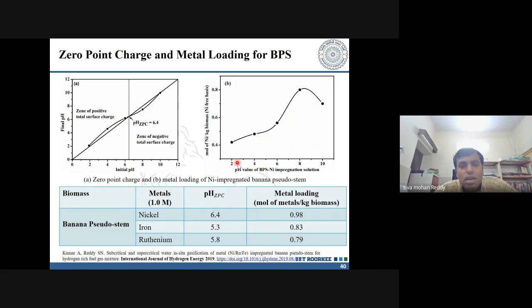You see this is pH, and this is the mole of nickel per kg of biomass. Now, even at the higher pH, you see the metal loading is a little bit high at 8, but after that it decreases at 10. The reason might be that during your impregnation, it forms precipitates of your metals, which get onto the surface, and as soon as you wipe it off, it is going to be reduced.